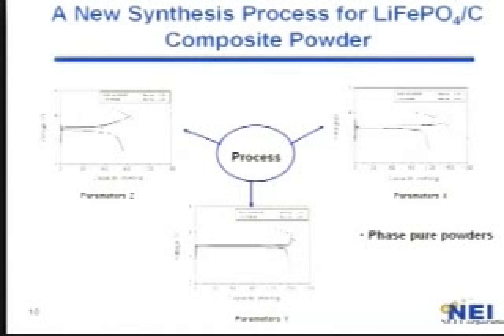the different processing parameters, one can achieve a very bad electrochemical material where the capacity is only 90, and by the way, the theoretical capacity of lithium iron phosphate is around 170 milliamp hour per gram. Further improving it, we had 120, but if you look at the first cycle charge capacity and the first discharge capacity, what we call in electrochemistry irreversible capacity loss was still higher. Then we further improved the process, and we could get almost 150 milliamp hour per gram capacity with only 3% irreversible capacity loss, which is acceptable for the battery industry.